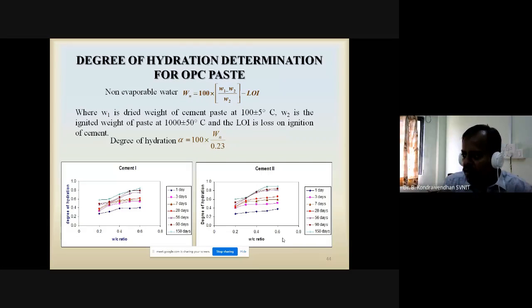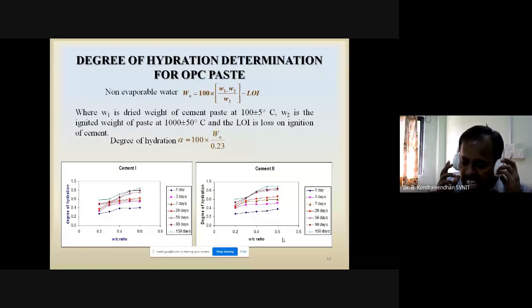The mixing water, whatever water we use for mixing, for example concrete or cement paste, consists of 2 types of water. One is evaporable water, another is non-evaporable water. Evaporable water one can determine by heating the sample to 100 degrees Celsius. But how to determine the non-evaporable water? If you are able to determine the non-evaporable water, it is also possible to determine the degree of hydration.